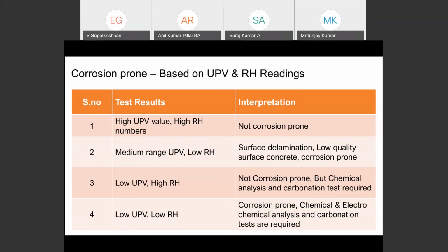Low UPV, high rebound hammer: it may not be corrosion prone, but chemical analysis and carbonation tests are required to understand the carbonation depth or the corrosion activity. Low UPV and low rebound is definitely corrosion prone. Chemical analysis is required, and carbonation tests are also required to assess this quality.